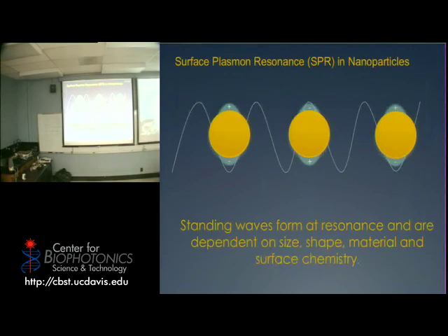You create on the surface these sort of waves, called evanescent waves, or also plasmon resonance, because this material at a specific wavelength creates a standing wave. So it's like the string of a guitar. You hit it and it plays a certain note at a certain pitch. That's exactly the same thing. At a certain wavelength, this movement of electrons starts to resonate. So if you look at it, you cannot really distinguish it moving back and forth anymore, although it is, but it's doing it at resonant frequency. And you create on the surface this resonance, this kind of cloud of electrons where you have a very intense electrostatic, electromagnetic field.